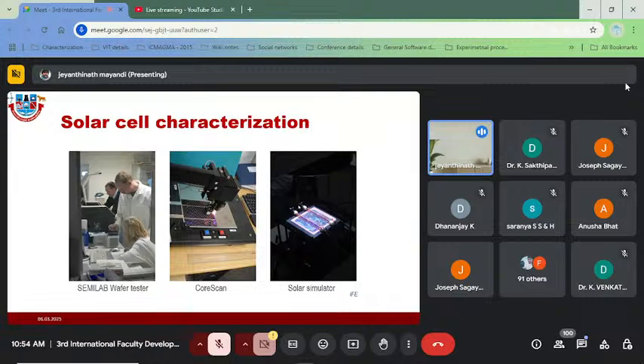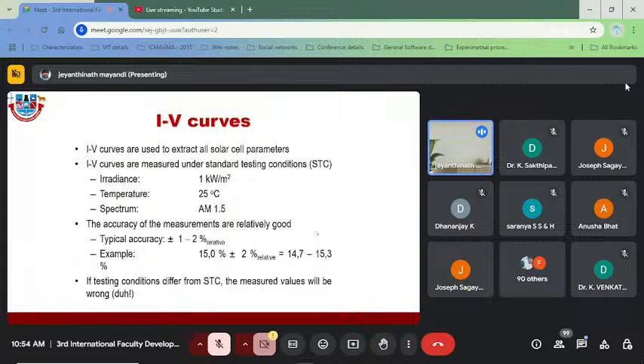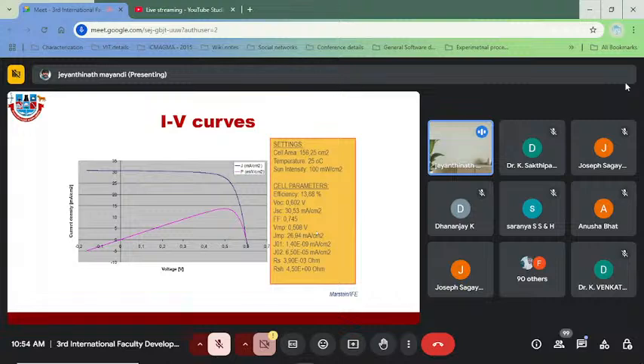Once the solar cell is made, it can be tested in different ways. To understand the contact establishment, one has to use a Corescan or Semilab wafer tester, and to find the efficiency of solar cells, one needs a solar simulator with IV characteristics. These are the process parameters for extracting the IV curves of a solar cell. With these conditions, one can measure the efficiency, and here are the measured values and cell parameters. For this particular case, the efficiency is almost 13.68 percent, the open circuit voltage is 0.6 V, and the short circuit current is almost 30.53 milliamps per centimeter squared.